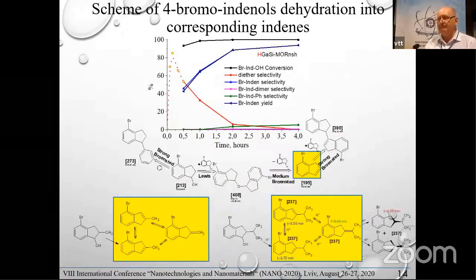The mechanism of this transformation includes formation of a diether, and this is the reason why there must be optimal acidity, optimal strength of acid centers, because in the case of very strong centers, there can be side processes, for example alkylation or semi-alkylation, with a decrease in the yield of the needed compounds.